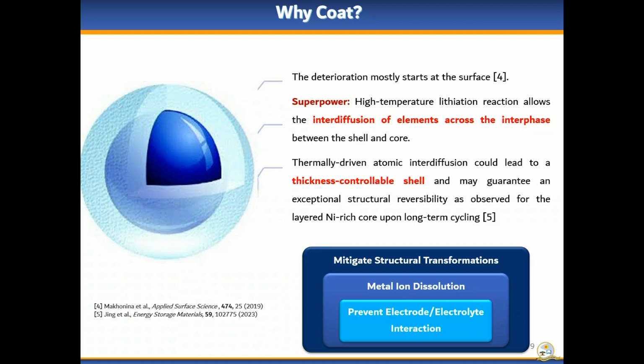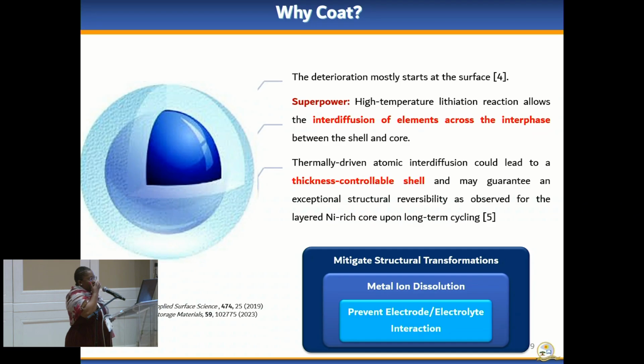So coming to what we're trying to do in the current study, this is from an MSc study by Precious Makubela. She could not be with us, so I'm presenting the talk on her behalf. What happens is that we decided to coat our materials because we know that the deterioration of the cathode material begins at the surface. What has been observed in previous studies is that the core shell systems have a superpower, that is, they allow for interdiffusion of elements between the core and the shell instead of elemental loss into the electrolyte. And this can also assist by controlling the thickness of the shell material, where you are able to sustain the structural stability of your cathode material.